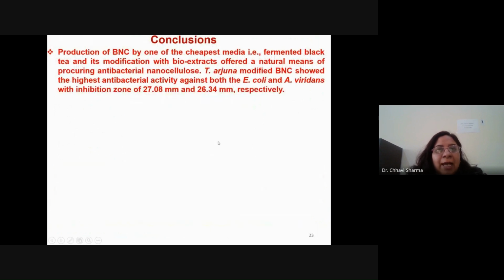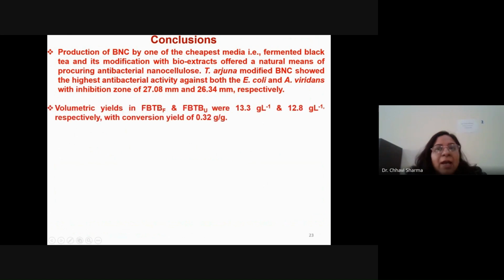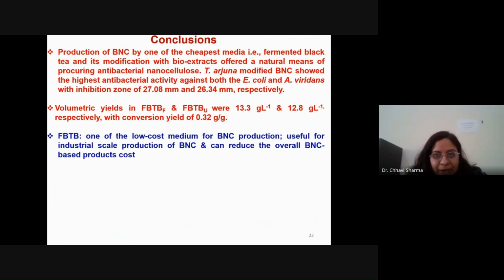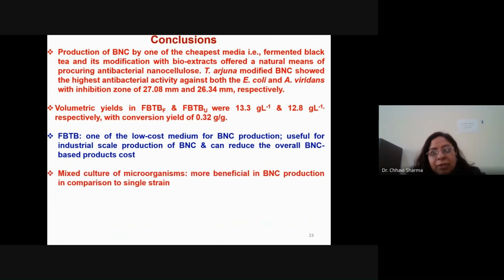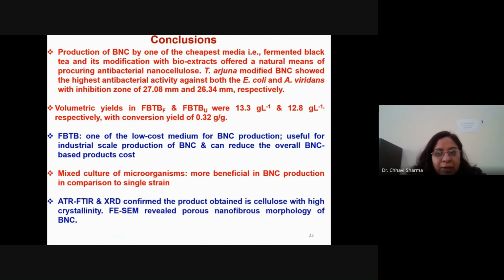So in conclusion, I would like to state that bacterial nanocellulose can be produced using one of the cheapest media, that is fermented black tea broth medium, and an all-natural antibacterial film can be made by modifying the bacterial nanocellulose using the bioextract. The volumetric yield in this case is about 13.3 gram per liter. Fermented black tea broth medium can be a low-cost medium and is useful for industrial scale production of BNC. And of course, the mixed culture of microorganisms could be more beneficial than a single strain.